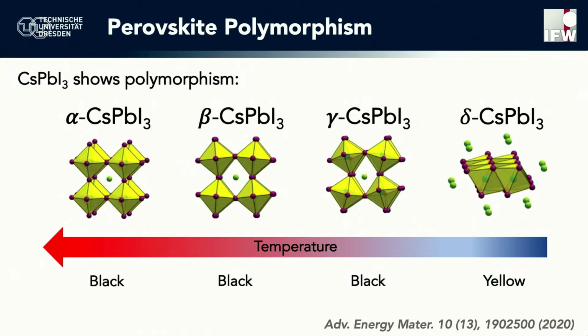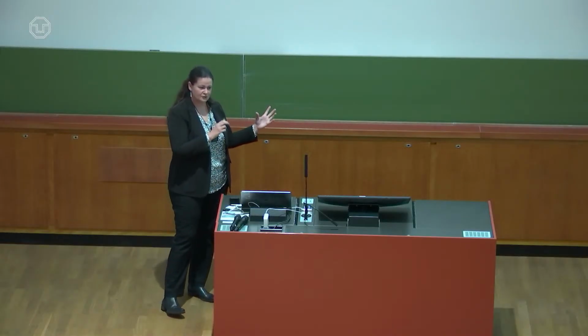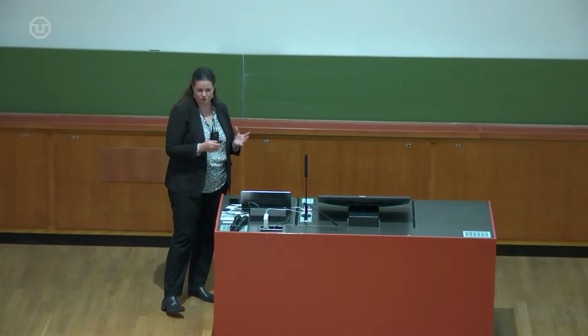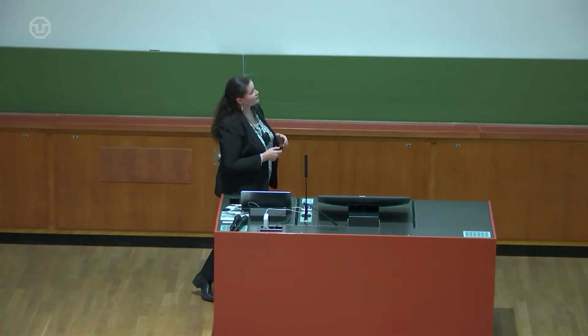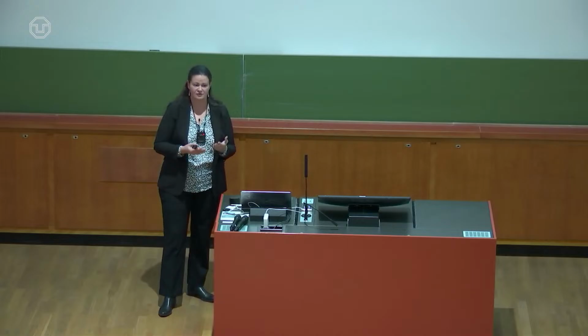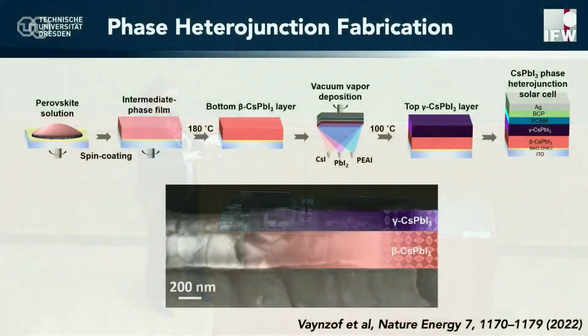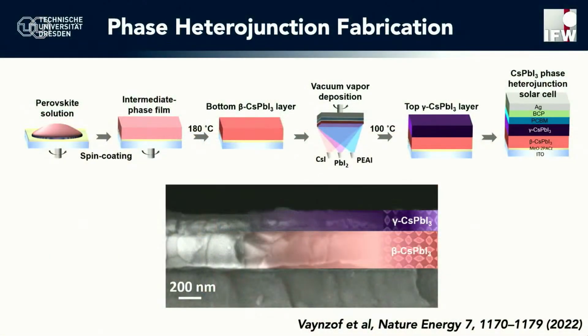You can also see that 3 of them, the alpha, beta, and gamma, are black, and so interesting for photovoltaics, while the delta one is yellow. It has a very large band gap, and it's really not very interesting. So we wanted to use 2 out of these 3 black phases to create the structure. And the way we did it is by combining the 2 methods for forming a perovskite. The bottom layer, the beta cesium lead iodide, was formed by spin coating, by solution processing. Now, once it was formed, we were not able to deposit the next layer by solution processing because we would have dissolved the first layer.